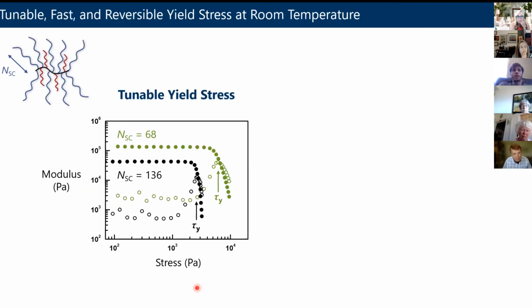And I want to jump to this rheology experiment, which is showing you how fast and how efficient the liquefaction is. So what you're looking at here is the stiffness, or that storage modulus from earlier in the talk. And depending on the bottlebrush side chain length, the stiffness changes a little bit. These are not cross-linked though. These are still viscous liquids. And as you crank up the stress, imagine like as you apply more force on a syringe, for example, this G prime value drops precipitously and the G double prime value in open symbols increases. And this transition right here is that solid to liquid transition.